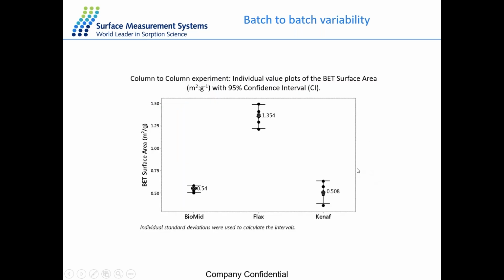So we've done a column-to-column experiment, using a few different columns and carrying out the BET surface areas. We want to understand the batch-to-batch variability between our samples. What's interesting here is that in our batch-to-batch reproducibility experiment, our natural fibers have quite a large variation in our different values for BET surface area. This can correspond to the irregularities and heterogeneity of our cellulose fibers, which is a result of them being natural. However, for our synthesized material, which is processed in a particular way to make sure they're all uniform, the batch-to-batch variability is very small. So this is quite interesting for understanding the difference between natural fibers and synthetic fibers.